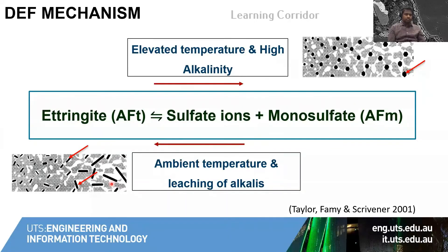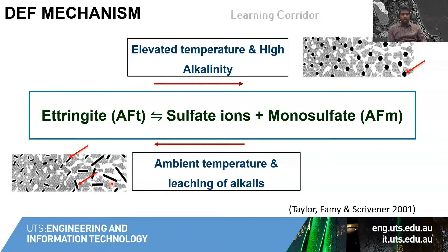Other analogous examples we can see are salt precipitation or water freezing in small pores — what happens because of the large volume-occupying tendency of any salt precipitation or water transferring from a liquid state to a hardened state in a small pore is that it may lead to cracks or expansion. Similarly, this ettringite precipitation occurring in concrete may also lead to cracks in the system.